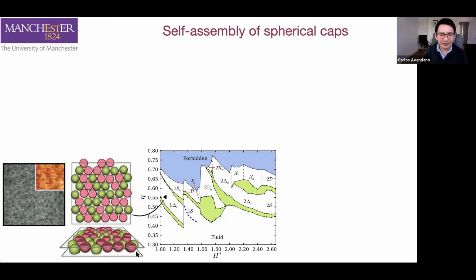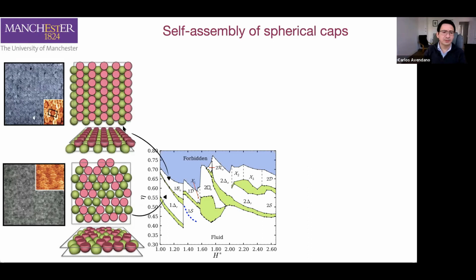Now, as soon as we increase the distance between the two hard walls confining the particles, it makes sense that some of the particles will be pushed up and some will be pushed down once that we increase the density in the system. And that's what we observe here. This is what we tend to call the buckle phase. And it's buckle phase because it forms some sort of undulations along this direction, which were again in agreement with the experimental observations from the group of Chekesha Liddell.